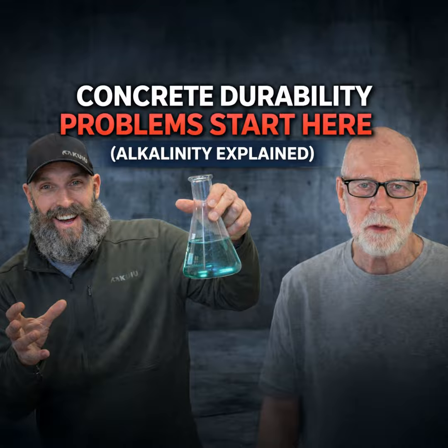Then water will push in and get much greater volume. But under normal circumstances, like a roadway surface, a bridge structure, or floor, you do not want a permeable surface because it absorbs water and it transports things in and out of the concrete. Because water's fine as long as it doesn't move. If you take a 3,000 psi concrete, leave it underwater and test it 50 years later, it'll probably be up around 12 to 13,000 psi.